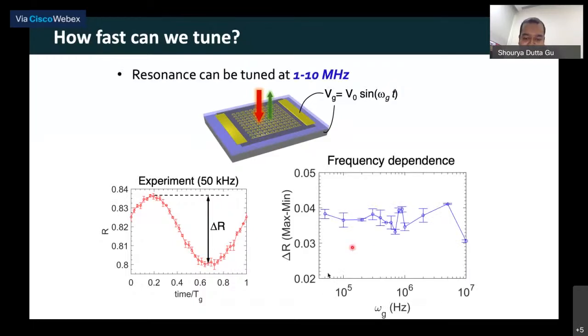Here we change the frequency of the gate voltage from around 10 to the power 4 hertz, 10,000 hertz, to around 10 to the power 7 hertz, which is 3 orders of magnitude. What we see is that during this whole range, which was limited by our instrument, we can get the same kind of delta R, which is the signal. What this is telling us is that even at these high frequencies of 10 to the power 7 hertz, we can still get the same response.